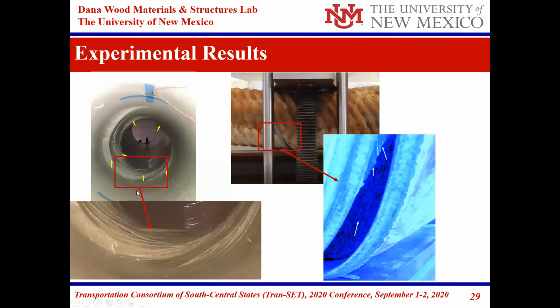Pictures here just showing failure of the GFRP in that case as well, which means full load transfer, and the fact that the pipe is corroded did not make any issue on the load transfer with the grout. This is the thermal picture showing that actually the opening is very large in the case of corroded pipe, and you can actually see now the GFRP and the grout being cracked. So that would be the key point in this, that we have to have enough strength at the seamless joint. This is the deflected shape.